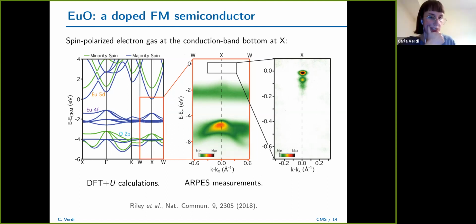So we discussed it briefly with Phil King, who did the experiments, but we didn't do any calculations. What the experimentalists observed was that these polaronic features disappear very quickly with increasing temperature, actually well before hitting the Curie temperature. So in practice, we did not try to explore this further, and I can't really speculate much on what the implications are for modulating the ferromagnetic temperature.